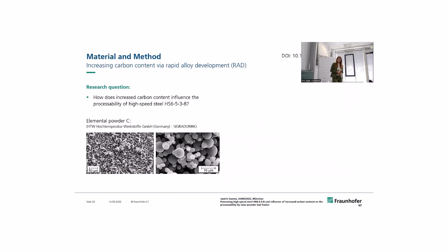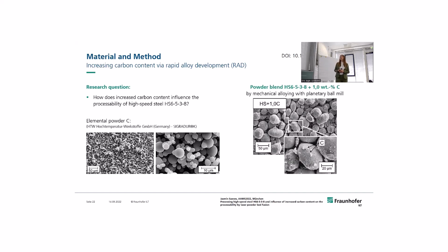How did we do it? We used elemental powder, carbon, but not graphite, which is usually used, but more, it's called glass-like carbon, which should be more stable, especially if you talk about mechanical alloying, which we did. So we used mechanical alloying, as we heard from Markus in the previous talk, by planetary ball mill, and added 1% of carbon. So that's the highest amount that we added, and we have the 2 lower sets as well. And we saw that it was quite feasible.